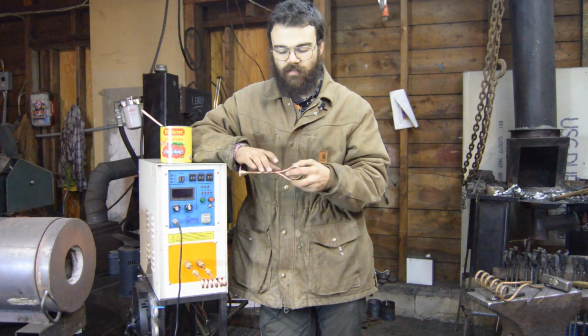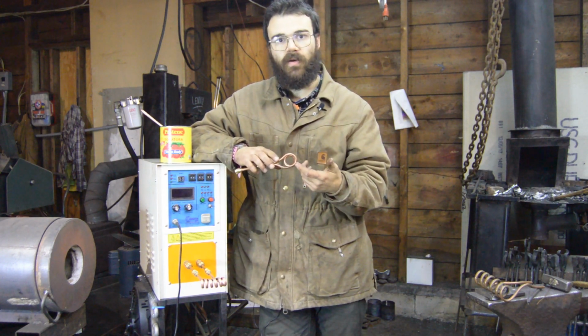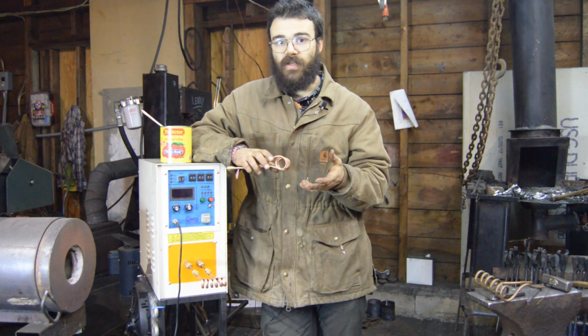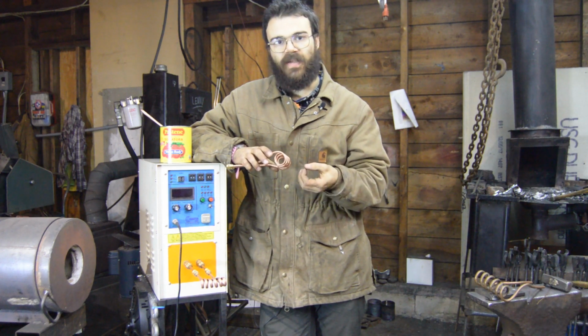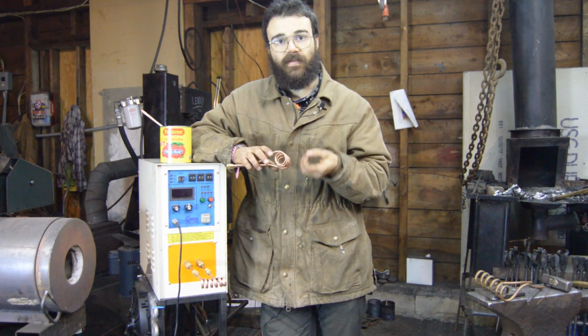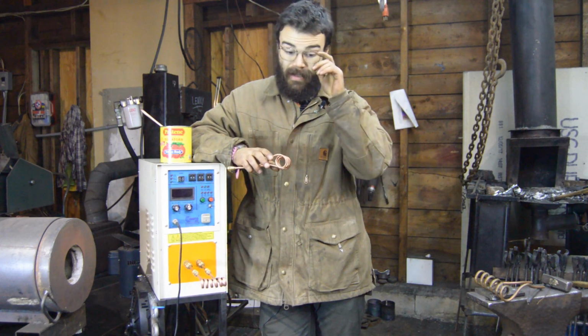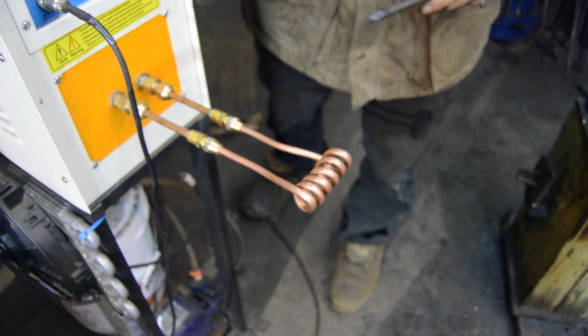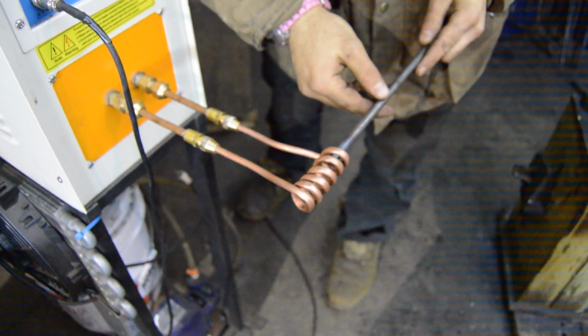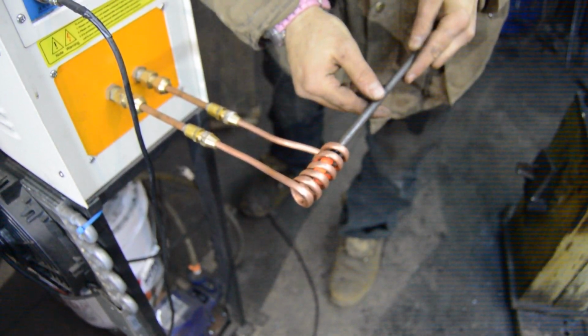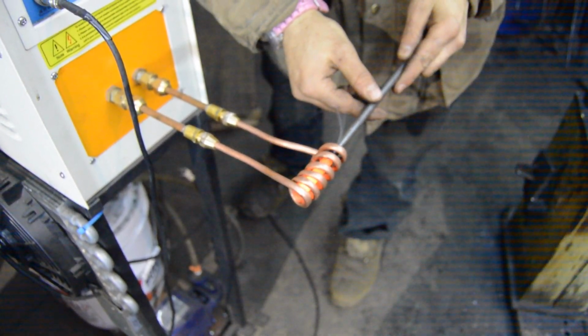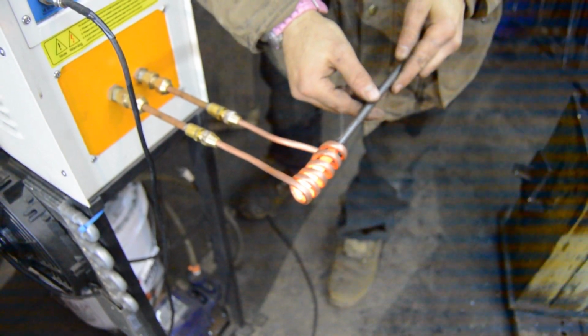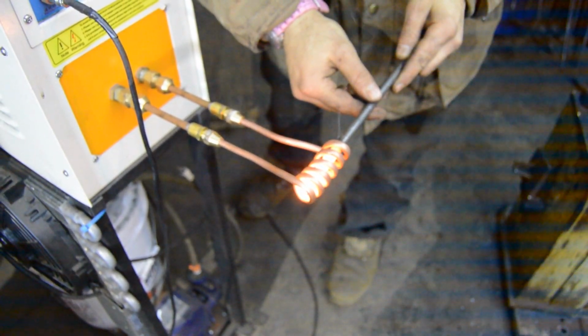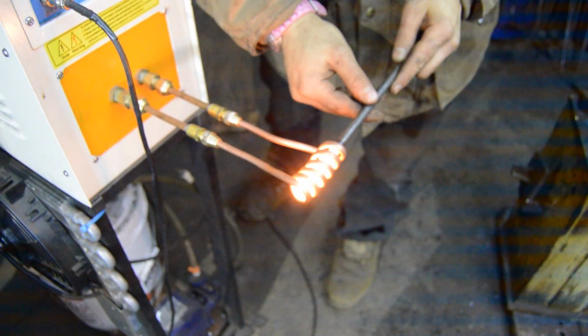So I guess the first principle of coil design is that you want to use the smallest coil for the job at hand. The reason you want to do that is because a smaller coil basically chokes down the inner part of the toroid that I talked about before, and it concentrates those magnetic field lines in the material, and you get a faster heating rate. This is a 5/8 of an inch inner diameter coil, and it'll bring 3/8 of an inch material up to a welding heat in about 15 seconds. But anything smaller than that, you start to see a diminished heating rate.